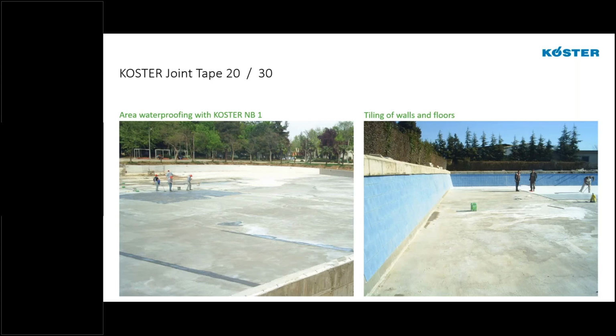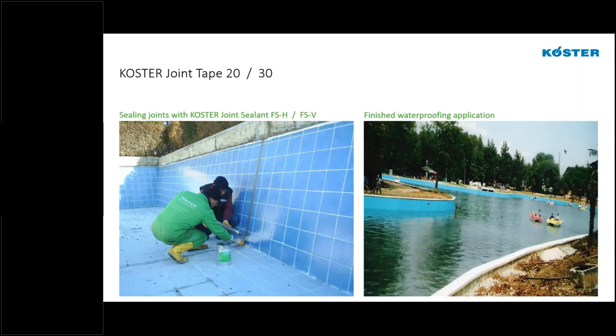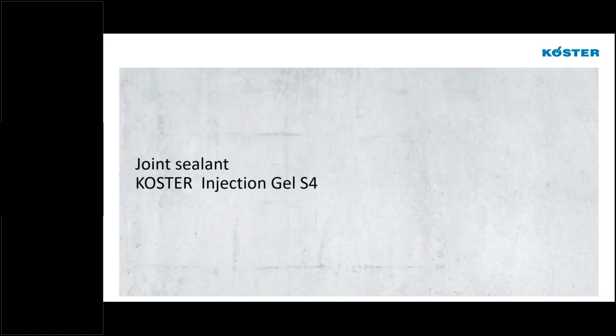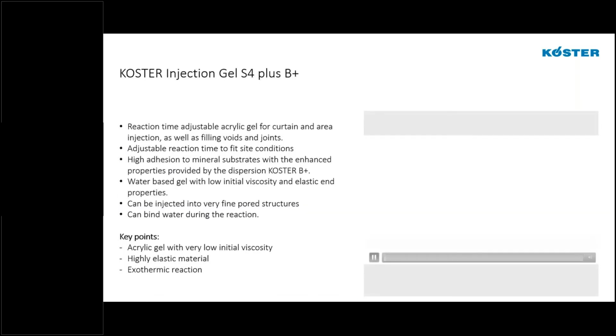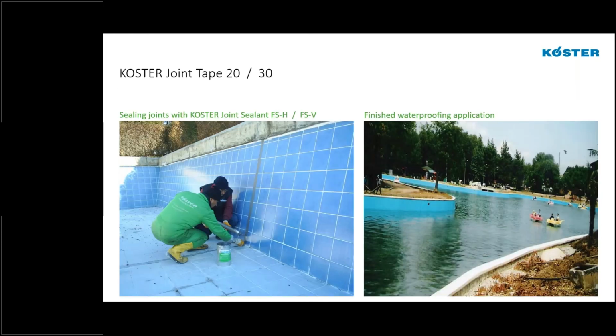Again, we have more pictures of the NB1 being installed on the wall and the floors, and then we have tile actually installed on the wall and floors over the NB1. The joints in the tile, the vertical joints, again, are sealed with the FSV, and then the finished application is obviously exposed to water from the positive and negative side as a pool, and has that long-lasting function with no water ingress or egress from any of the joints in the structure.